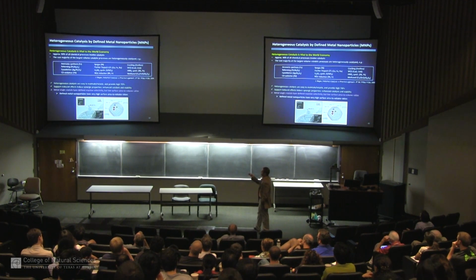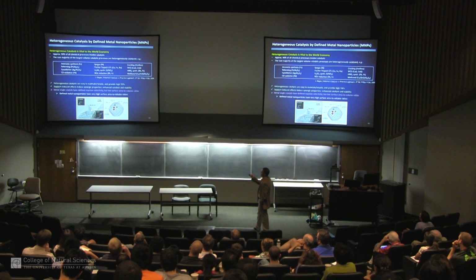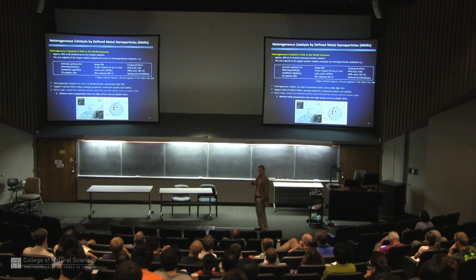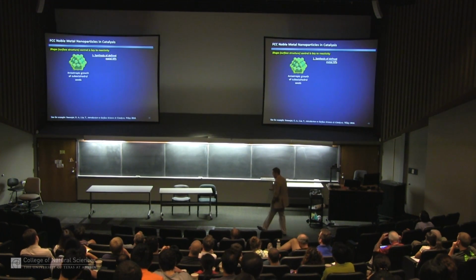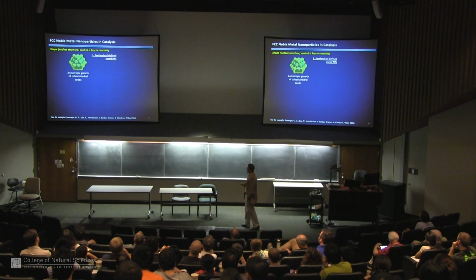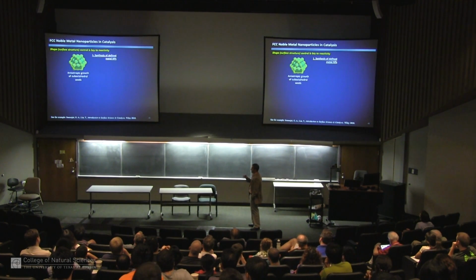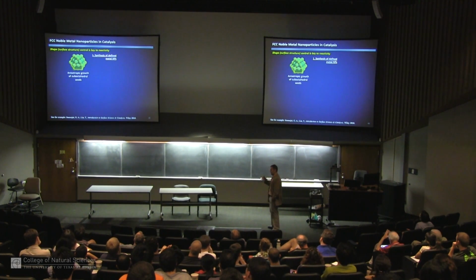And so here you can see there's a rhodium particle that's anchored onto some oxide material. This is very useful because you've got a lot of surface area and not much volume. And that's important. We want to use as much of the metal as we can. If it's heterogeneous catalysis, it's only the surface that counts because it's only the surface that's exposed. And so our thinking in this is to grow particles that have very defined properties, both composition-wise and structurally, so that we can try and improve upon existing catalysts for simple reactions. Now, these are simple reactions that you shouldn't belittle just because we're doing hydrogenation of simple alkenes, for example.